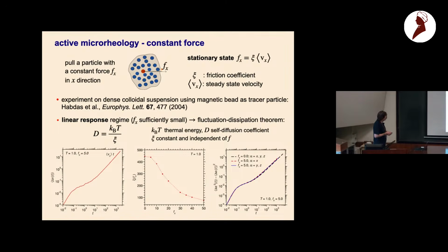And in fact, if we go to this point here, where we are close to the linear response, all the MSDs, this is corrected in the force direction by the drift motion, so we subtract this. And in force direction, all the MSDs agree with that obtained in equilibrium.